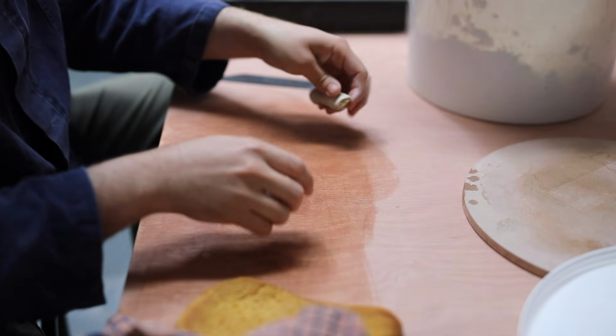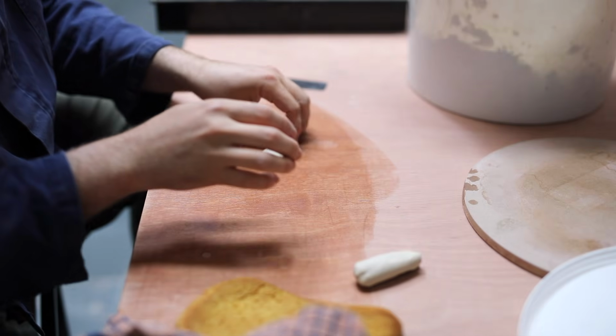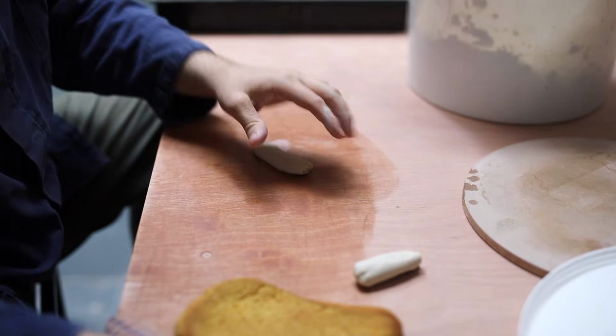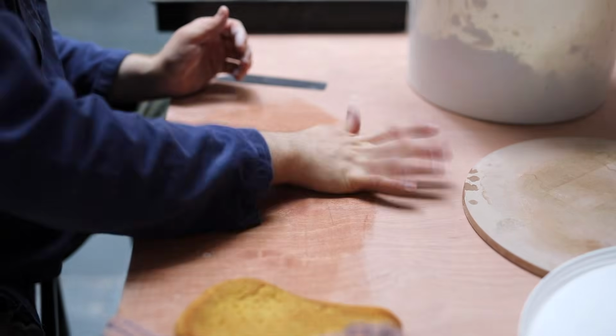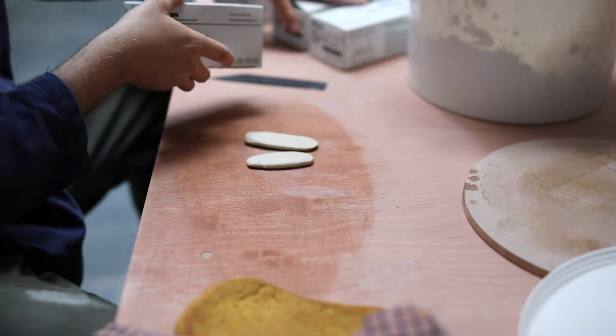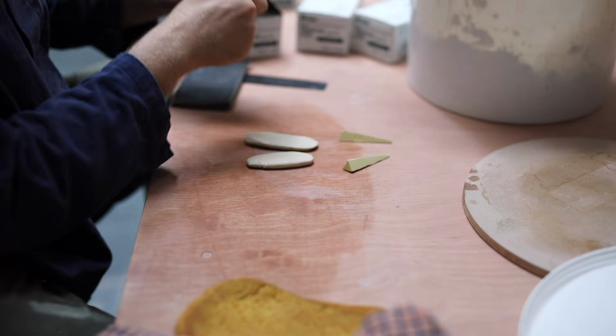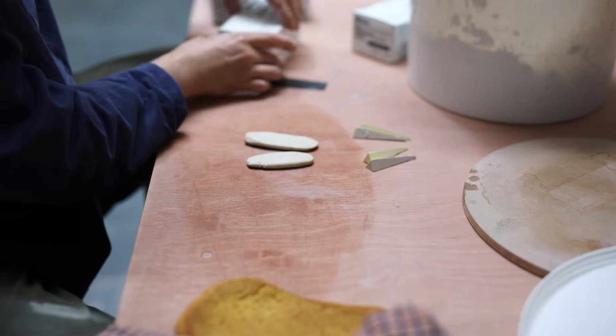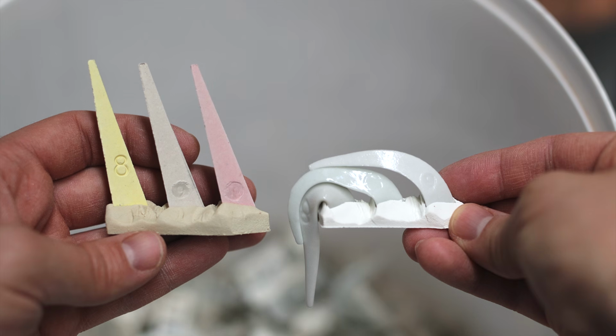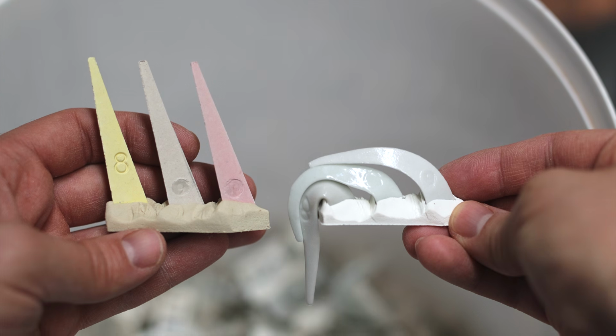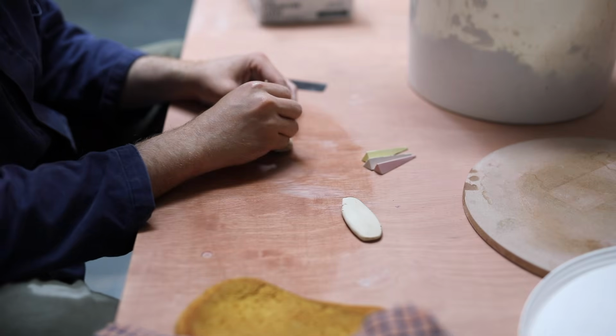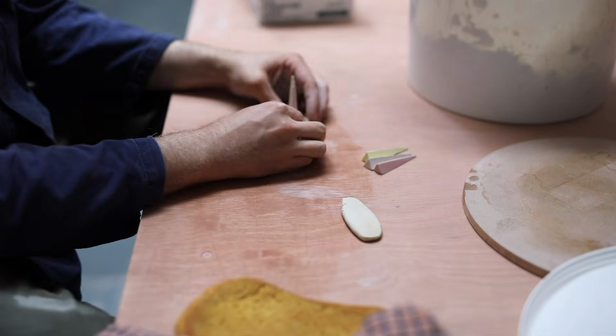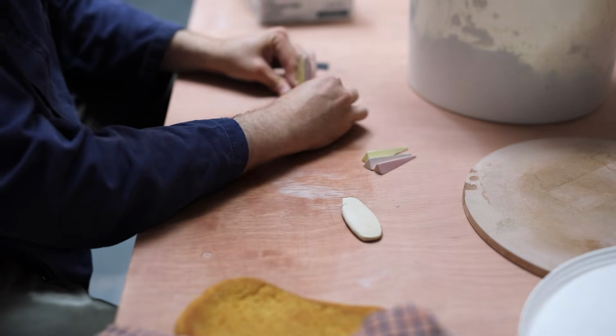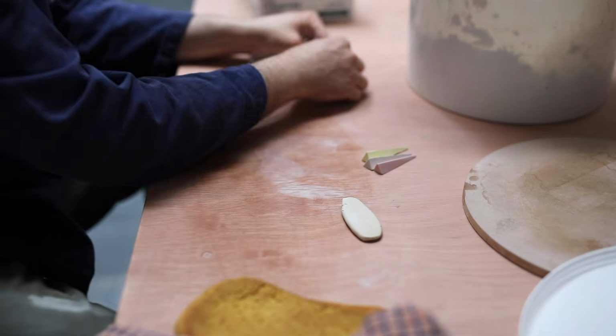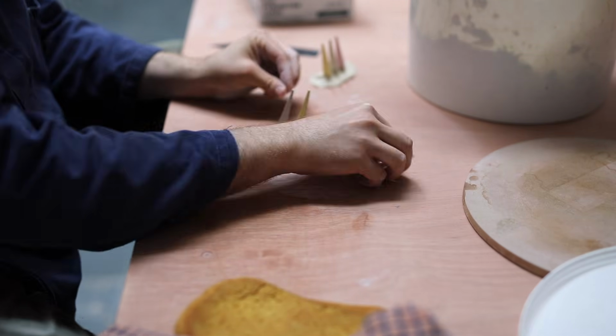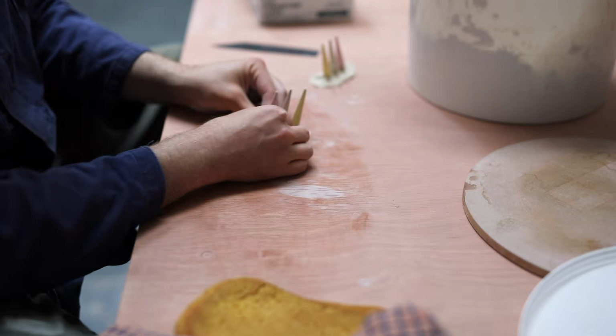The next task I have to do is make some cone packs. This white stuff is wadding, and it's essentially the same recipe as the bat wash I was painting onto the kiln shelves. Both are made from 50% coarse alumina hydrate and 50% china clay. Only one has much more water added to it than the other. These cones measure heat over time during the firing, and they're positioned inside the kiln opposite the spy holes in the door. This way I can see them, albeit quite difficult at times, especially during reduction, when more flames are swirling around inside the chamber.